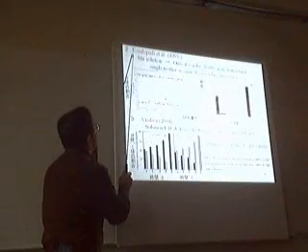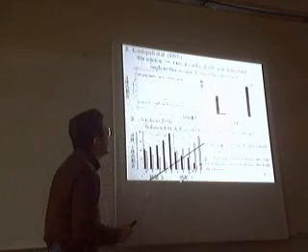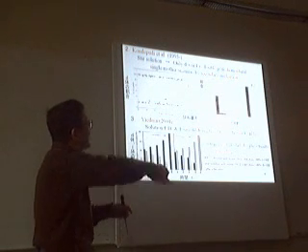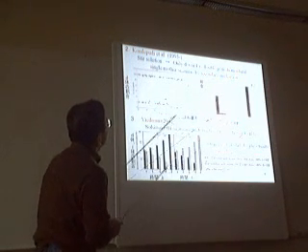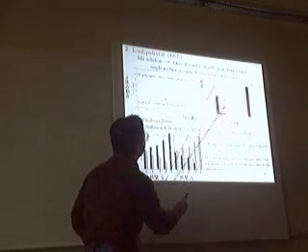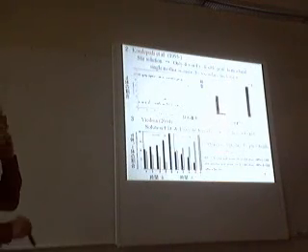And the next experiment was conducted by Kondepudi and his group. He prepared the solution and then stirred it. Then he obtained D type or L type, with 100% homochiral crystal.